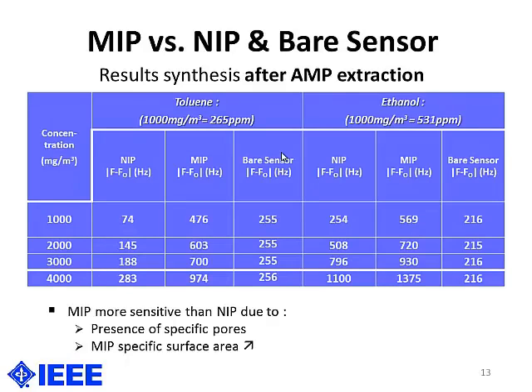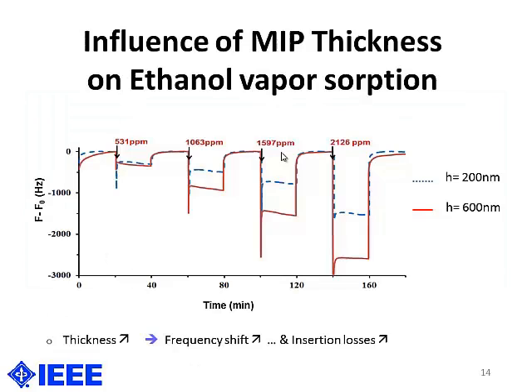This table summarizes the main results. So we can see the bare sensor that has the same responses whatever the vapor concentrations, and the same one for ethanol compared to toluene. And we can note, of course, also the greater sensitivity of the MIP-coated device compared to the non-imprinted polymer-coated device. As expected, of course, the same for ethanol. So this is due, of course, to the presence of specific pores in the MIP, and so then greater surface area.